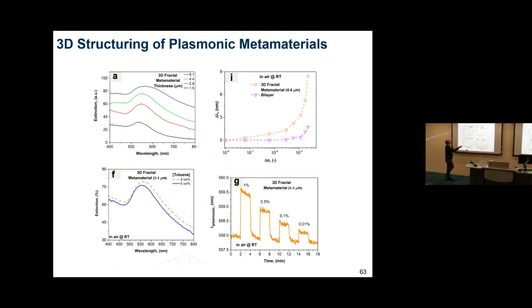When you do that, you can see the three-dimensional fractal metamaterial has a much higher response than what I showed you before. Therefore, we were actually able to go down to 0.01%. We're approaching now ppm level at room temperature with this optical sensing technology.